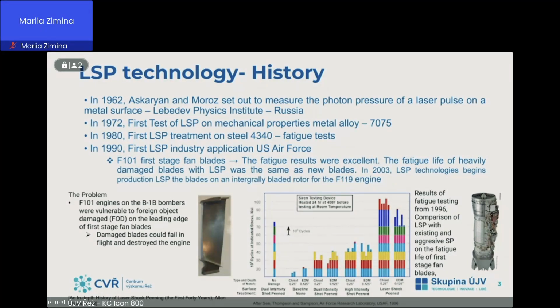And a very important date is 1990. It was the first industry application for the US Air Force on the F101 engine, for the first stage of fan blades. Because this engine had a problem: the B-1B bombers were vulnerable to foreign object damage on the leading edge, and the damaged blades could fail in flight and destroy the whole engine. It was a very big problem because servicing of these engines was very frequent, and it was very expensive.